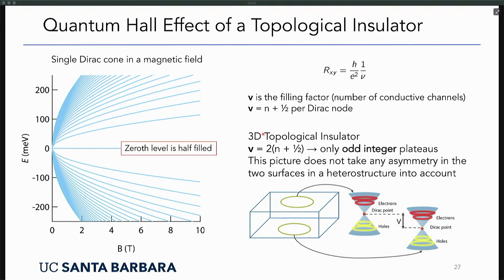So for a 3D topological insulator, this should produce filling sequences n plus 1/2. Okay, this 1/2 is special for Dirac nodes. And if you have a topological insulator where we have a bottom and top surface, so we have two of these Dirac nodes, we get this degeneracy factor of 2. So 2 times n plus 1/2. So then you would calculate that the filling factors ν that you should see in this quantum Hall effect that I just showed you, you should only get odd integer plateaus, right? So 0, you can work this out. Okay, so normally in a 3D topological insulator, you would expect only odd plateaus. So this already gives you a hint why we have these very strong odd integer plateaus.